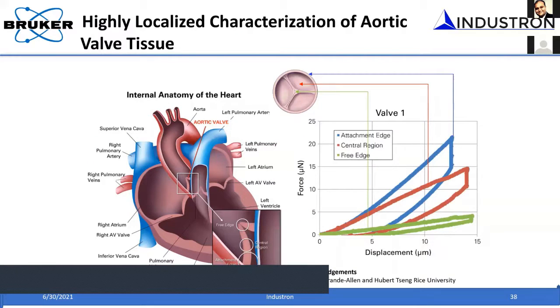supposed to be. So in this particular case, if you do an indentation experiment at the periphery where that opening happens, it should be more elastic. At the point where it is anchored, it should be more rigid, and the middle in between. So if you go and measure these properties at 3 different locations, you can see that the periphery where it is supposed to be rigid, it is very stiff. At the periphery where it's supposed to be elastic to have conforming closure of the wall, you can see it is highly elastic. So using this kind of technique that we have, this indentation technique, we can go and probe and understand, and then we can design materials accordingly.